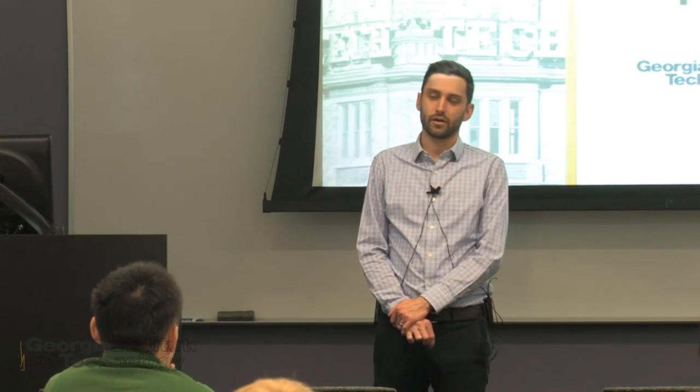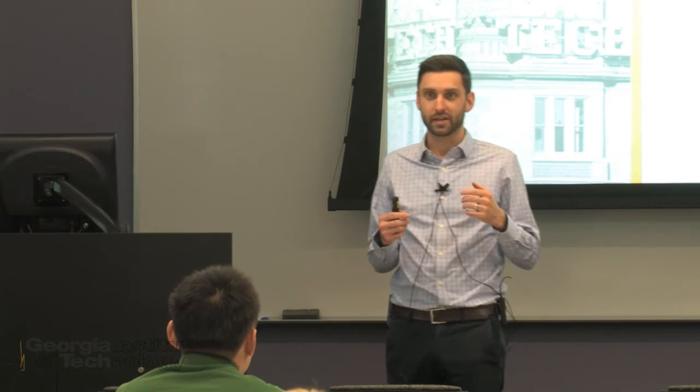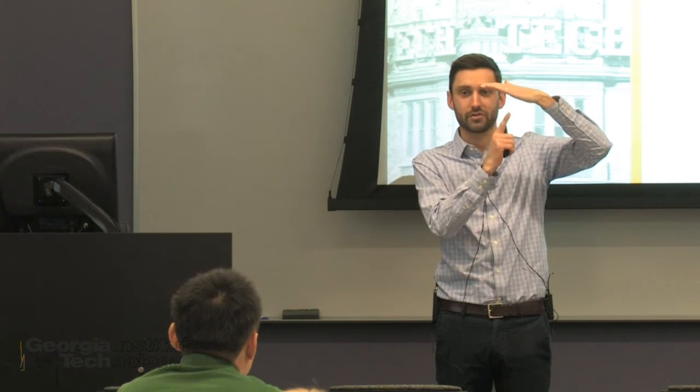I just want to know if the lithiation process is affected by the electric field and the direction of the lithium-ion flux. Are you asking about the specifics of the in situ experiment, or just in general? What you show in the picture is quite uniform in all directions, but are you doing this in an electric field, or without any electric field? In a normal battery, the electric field is generally pretty uniform because you have parallel plates and a large surface area. In my in situ experiments, the electric field is highly concentrated because you have maybe a single nanowire and a counter electrode with a small gap. So you can have very high electric fields.